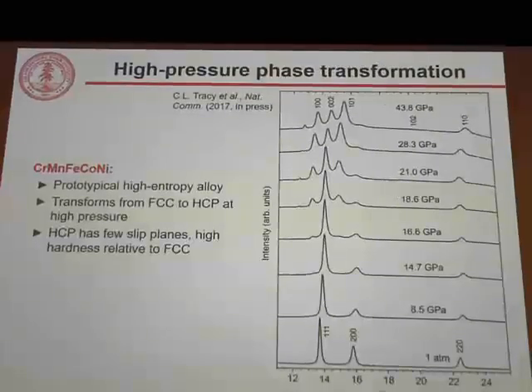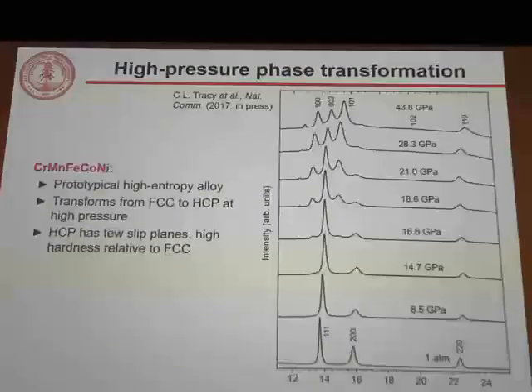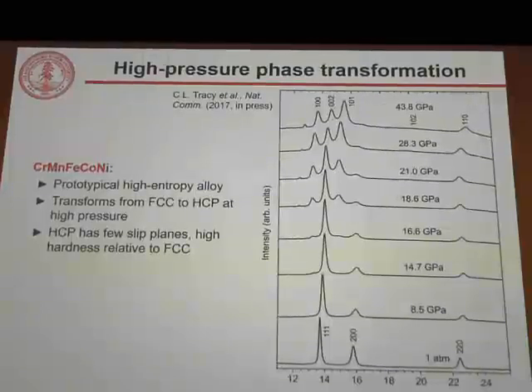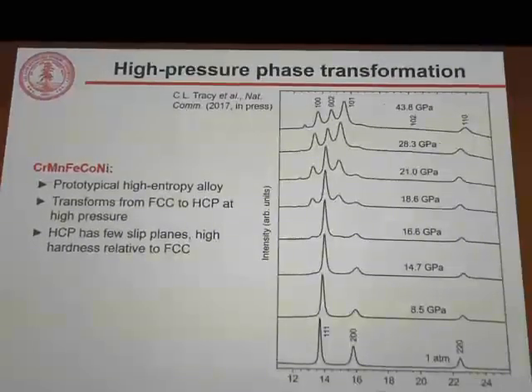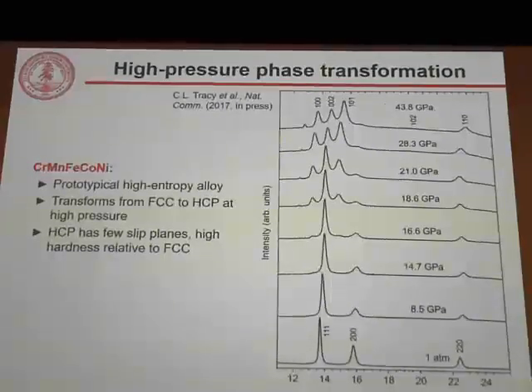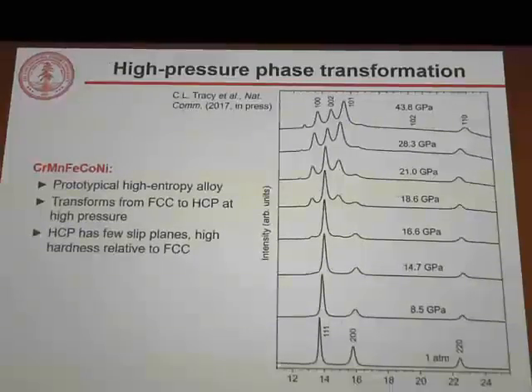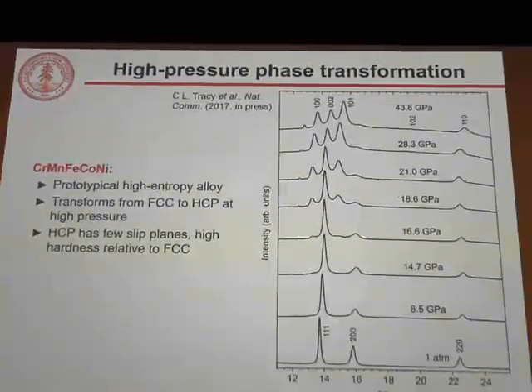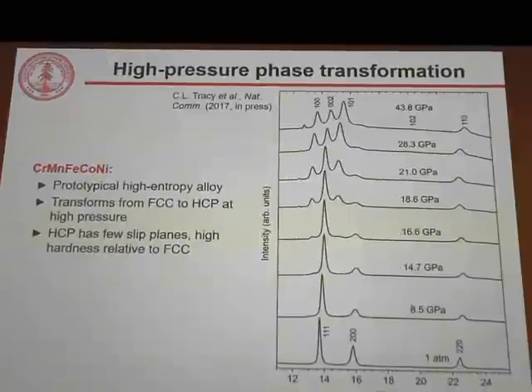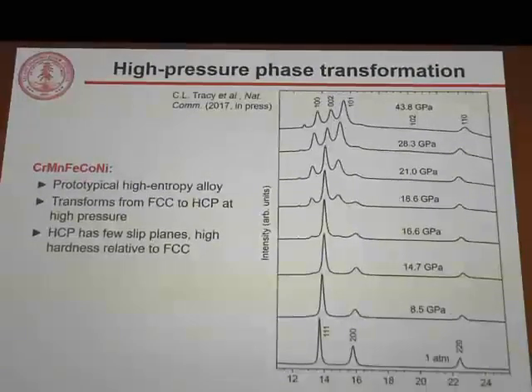In fact, when we pressurize this material, as shown in the XRD data here, starting with the ambient pressure XRD pattern and pressure increasing as we move up, we see a clear phase transformation of the prototypical high-entropy alloy chromium, manganese, iron, cobalt, nickel from the initial face-centered cubic structure to a hexagonal close-packed structure. This is what a lot of people have been trying to do.